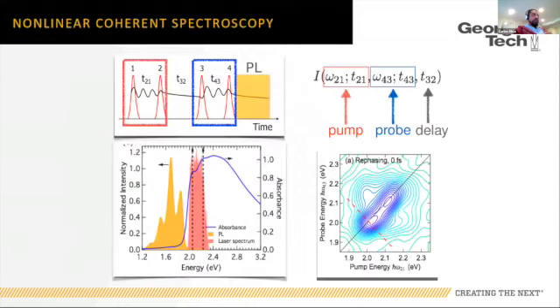So now I'm not going to tell you about the technique. I'm just going to say that I use a two-dimensional spectroscopy technique where I take a sequence of femtosecond laser pulses, 4 pulses, with a very well-defined phase relationship between a pair and another pair, two pairs with a well-defined phase relationship that I defined by acousto-optic phase modulation. So these are phase modulated, these are phase modulated.